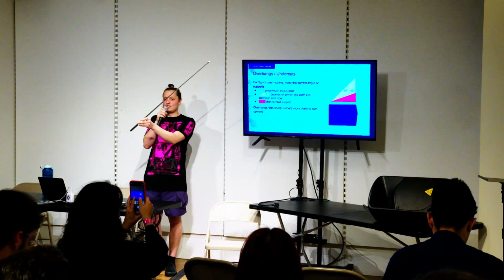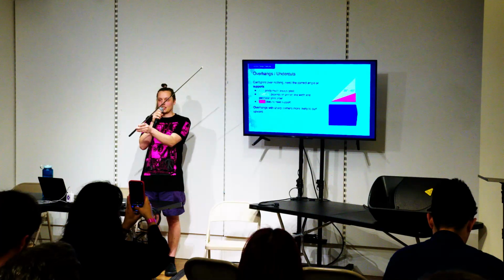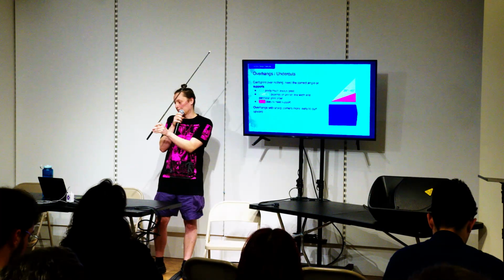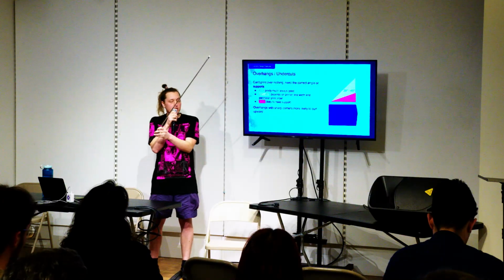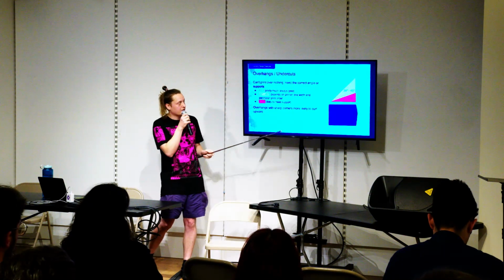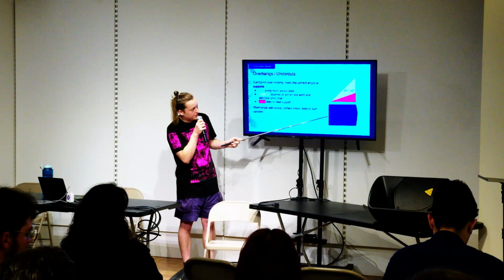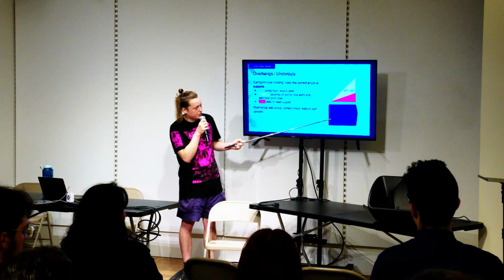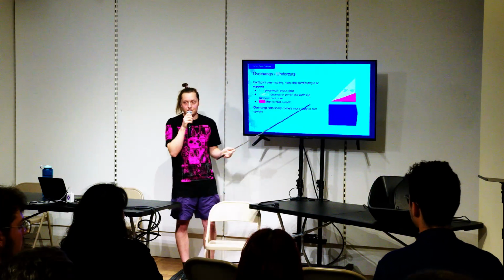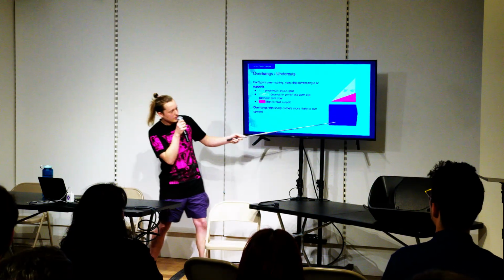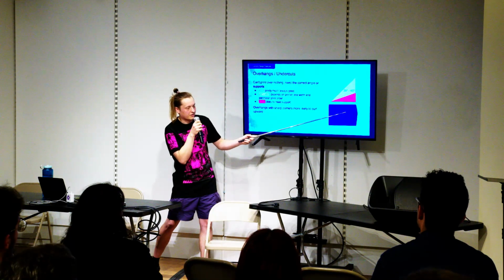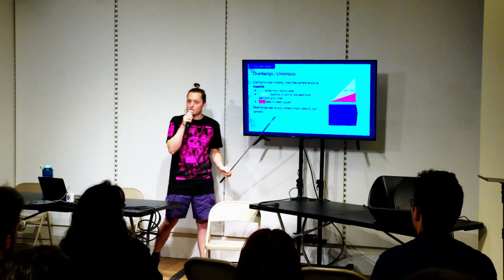In general, any time you have an overhang that's at 45 degrees or larger, your print should do perfectly fine without any supports. As you kind of get below that, you vary a little bit and might need supports. So you can see here, this surface is 45 and then drops by 10 to 35, 25, 15, and then 0. And as you get kind of into this 15, 20 range, you can see the surface quality starts to deteriorate without supports.